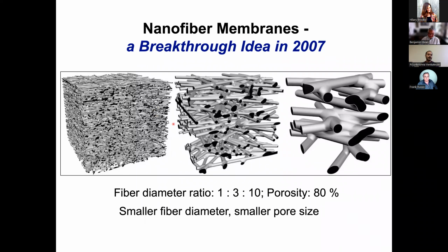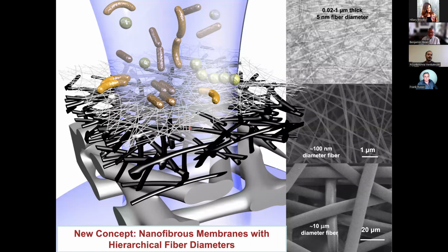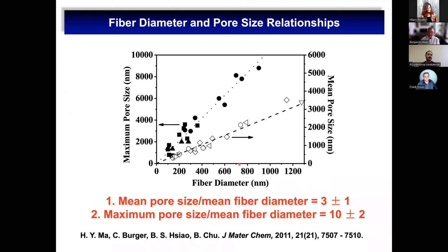So with this concept, we made membranes out of 3 different fiber diameters. One is a non-woven. The middle layer is this electrospun membrane, and there's the top layer. The electrospinning process is not suitable to make fibers with diameter less than 100 nanometers or so. So we came across a technology, which I'm going to talk much more about. It's called nanocellulose technology, with which we can make 5 nanometer fiber diameter. So we actually made the 3 layers of fibers for water purification.